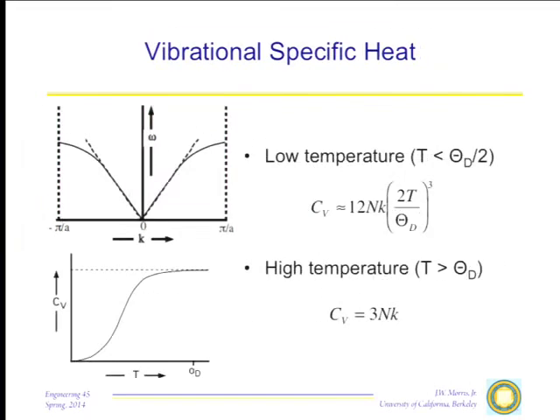The vibrational contribution to the specific heat: at high temperature, T above θ_Debye, the specific heat is simply 3Nk. At low temperature, C is proportional to (T/θ)³, taking off from T = 0. In between, we need a Debye interpolation formula which is in the notes. This intermediate region will differ from material to material. Near the Debye temperature it must bend over to asymptote toward the high-temperature behavior. This is why all solids have essentially the same specific heat dependence on the dimensionless temperature T/θ_Debye.